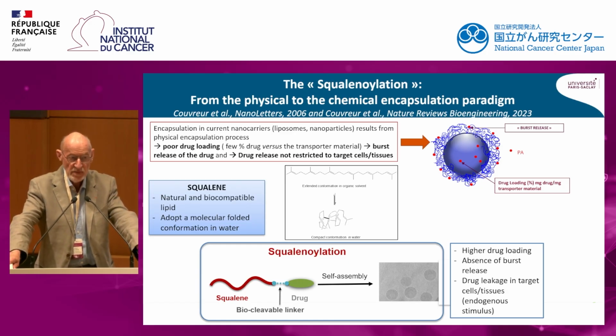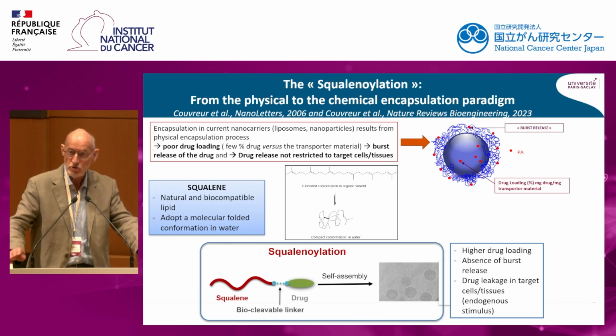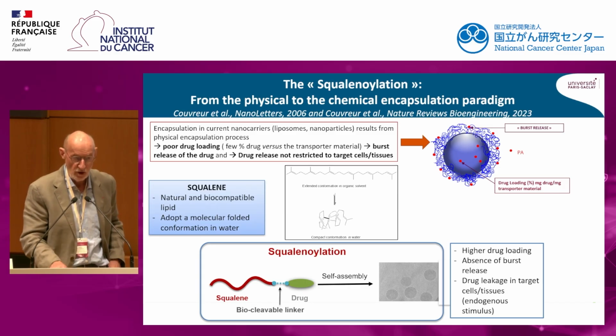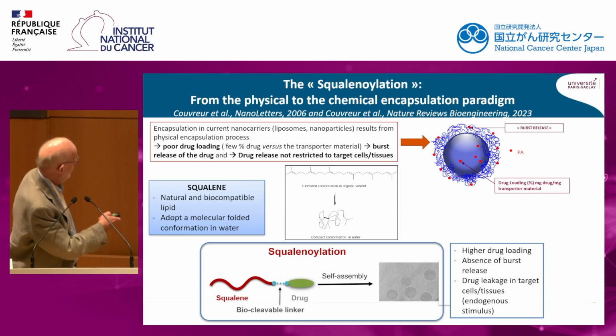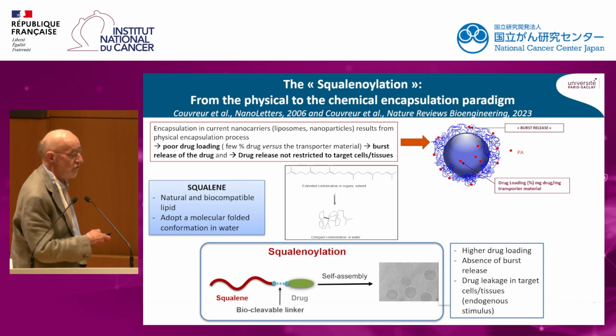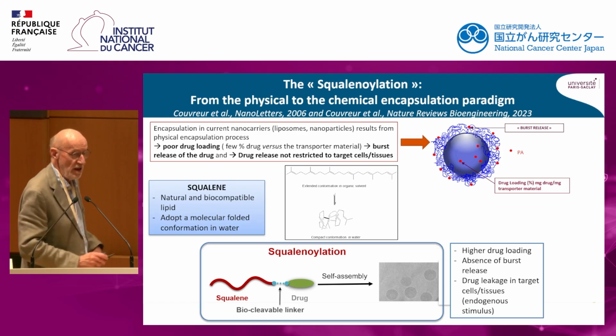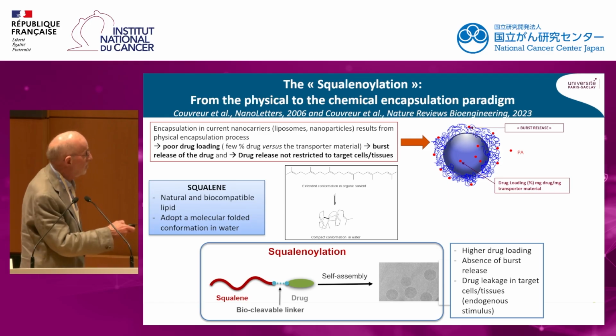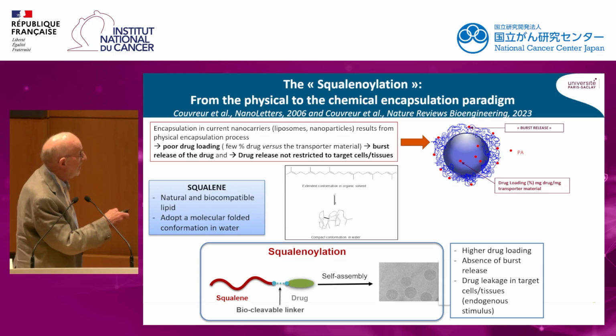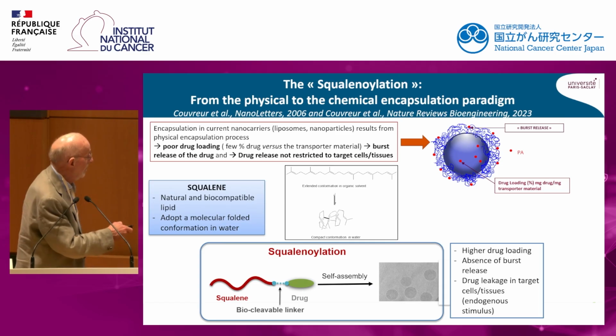And it is for that reason that we have moved from the physical to the chemical encapsulation paradigm. In other words, we did chemistry instead of physics. And to do that, we use squalene because it is a natural and biocompatible lipid. And amazingly, this natural lipid adopts in water a molecular folded conformation, as you can see here. And we have taken advantage of this compact conformation of the squalene in water to link to the squalene, used as a transporter material, several drugs through a chemical link.